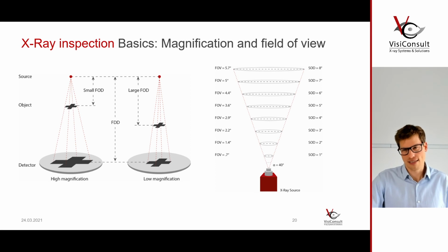One last hint, it's again a bit technical, is that X-ray is a cone beam technology, which means to achieve more resolution, right, you have to magnify. That means you have to move the part closer to your X-ray tube. If you do this, at the same time your field of view is reduced. Typical detectors that are used for computer tomography are 40 by 40 centimeters, right? And if you have a magnification of close to 1, so you're very close to the detector, you can scan a part of 40 by 40 centimeters. But you are limited to the resolution of the detector, let's say 100 micron. So your defect detectability is somewhere between 200 and 300 micron.